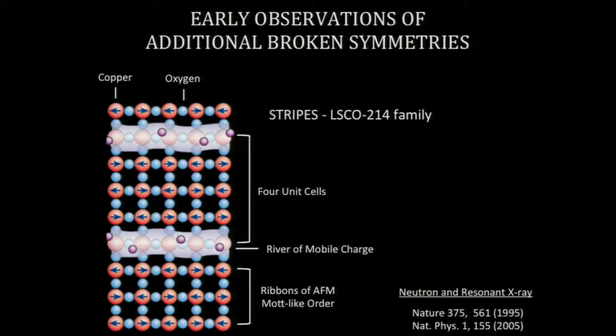Early on, though, when I showed you that phase diagram, there was evidence for additional broken symmetries in the system. So in the mid-1990s, neutron and X-ray measurements showed that in the lanthanum compounds there's this very odd structure in the copper oxide plane, where you had these rivers of mobile charge and then this antiferromagnetic insulator. So it looks like you've broken translational symmetry in that direction.